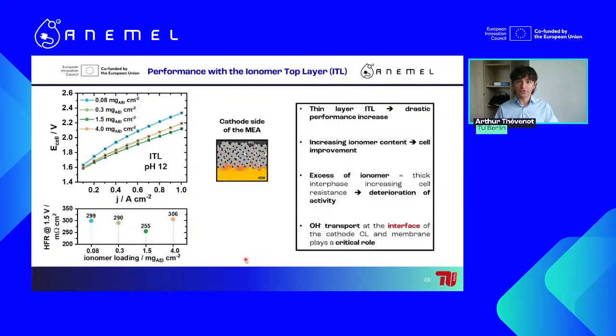And now, regarding the performance with this ionomer top layer, also in pH 12, we see that similar to the ICL configuration, with only very thin layers, so also 0.08 milligram ionomer per square centimeter, we already have a drastic performance increase. And we see that increasing the ionomer content also increases the performance of the cell, which is very interesting. However, having an excess of ionomer can be seen as a thick interphase, which will increase the cell resistance and also induce the deterioration of your activity. And this shows that the OH- transport at the interface, so at this two-dimensional frontier between the cathode catalyst layer and the membrane, plays a critical role.